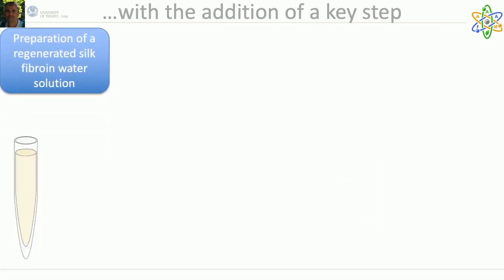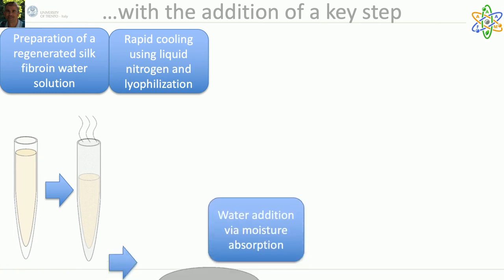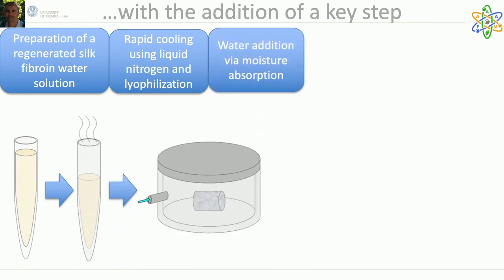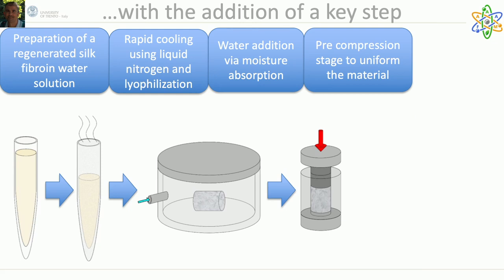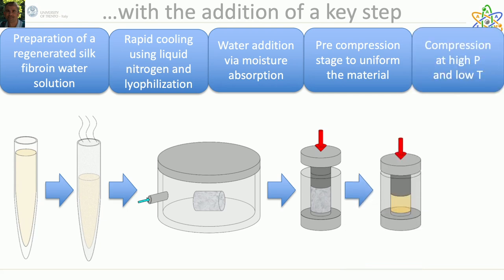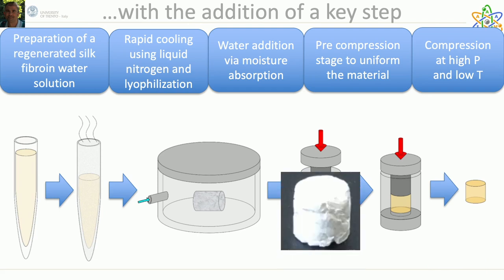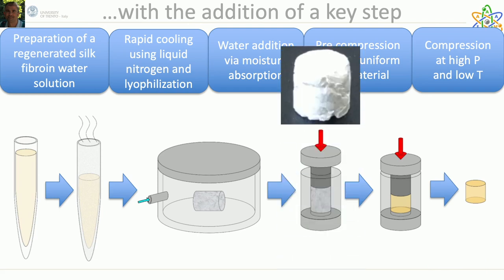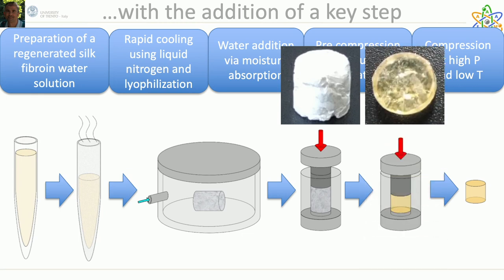We decided then to modify our approach and try using water as a plasticizer. We introduced a further step in the process, constituted of the hydration of the dry silk flakes for a short period in a closed humidity saturated chamber. Only by hydrating the silk powder with water for a few minutes, the material could be easily sintered, turning from a white compressed powder to a continuous semi-transparent chip.